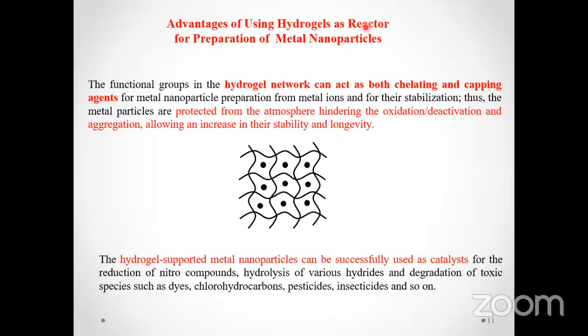So what are the advantages of using hydrogels as reactors for the preparation of metal nanoparticles? If we use the hydrogel networks as reactors, then these hydrogels can not only act as the reactor medium in which the metal nanoparticles can be prepared, but they can also act as chelating agents and capping agents for the stability of metal nanoparticles. So there is no need to add any additional capping agent. The metal nanoparticles are also protected from the atmosphere, hindering oxidation, deactivation and aggregation, thus increasing their stability and longevity. So this is how the hydrogels can be used as an advantageous material for the synthesis of nanoparticles.